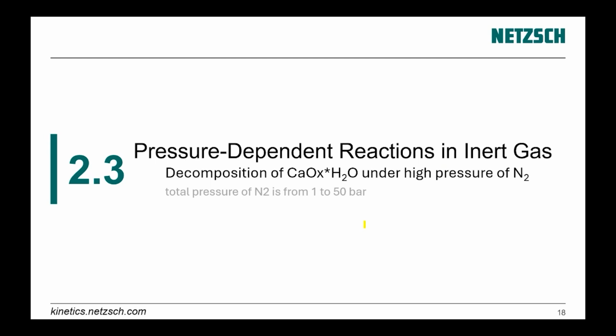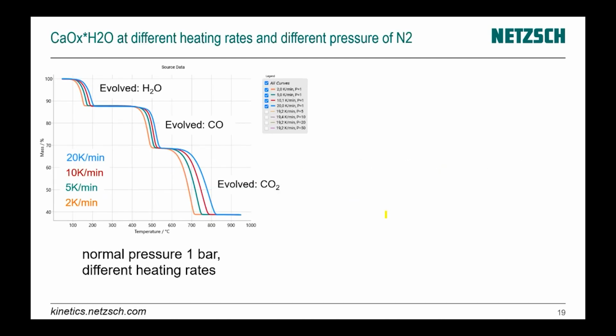Sometimes inert gas has also an influence on the reaction rate. And here is the example. We will make decomposition of calcium oxalate monohydrate under the high pressure of pure nitrogen. Here, the nitrogen is a non-reactive gas, and it is not present in the chemical equations if we write them for this decomposition. The measurements will be done in our high pressure STA only in pure nitrogen with the pressure from 1 to 50 bar. Let's go.